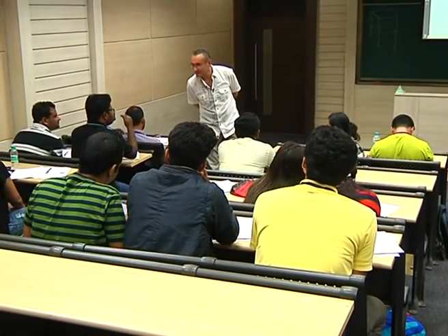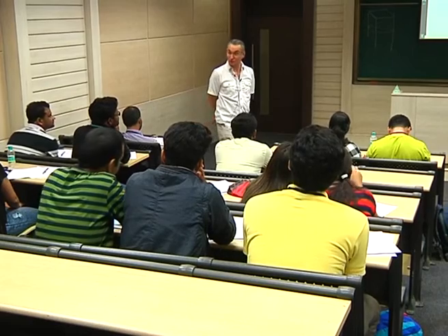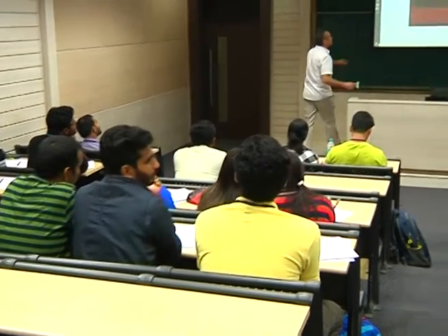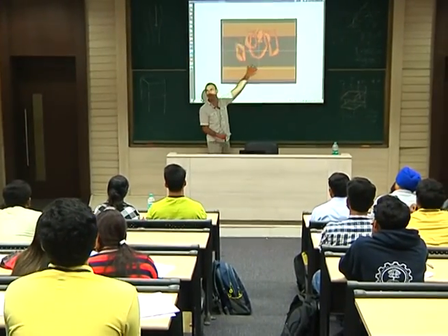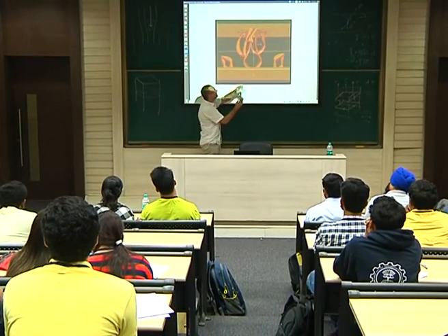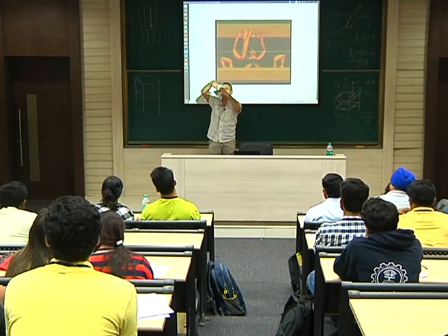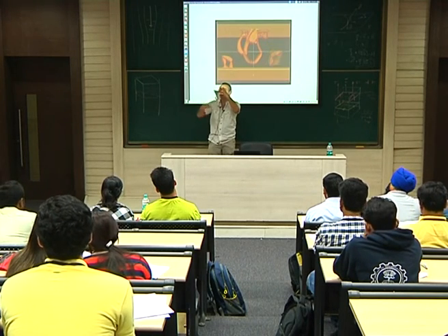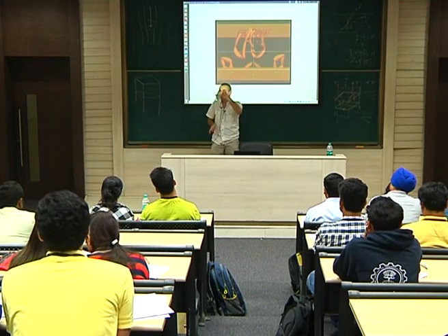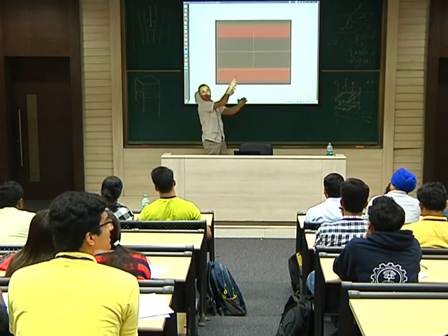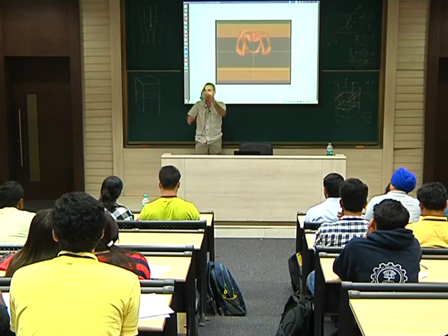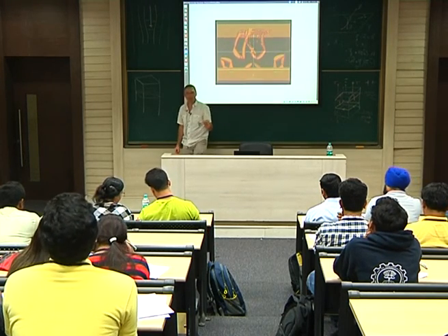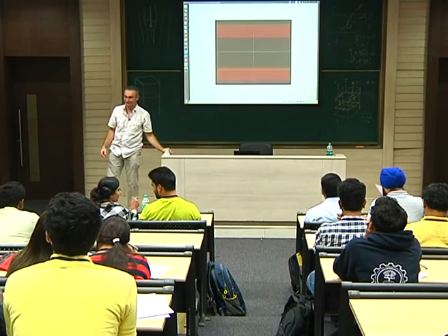The indentation what? Oh, this one, yes, that's a good question. Yes, I didn't say anything. This was the 111 plane. So yes, to illustrate this, but this is an example I will give later on, so we will see that in detail. This is the 111 plane, so we are pushing on that plane. And on that plane, you have three Burgers vectors, those three, which are activated. And you build your prismatic loops out of those three Burgers vectors. This explains why you have those three loops. Okay, you push here, and you have three loops expanding among those three directions. Okay, that's exactly it. That was a good question. Thank you for asking.